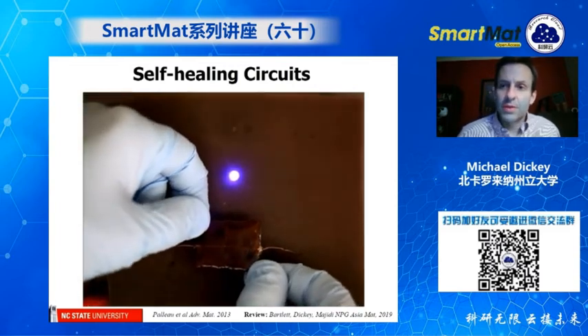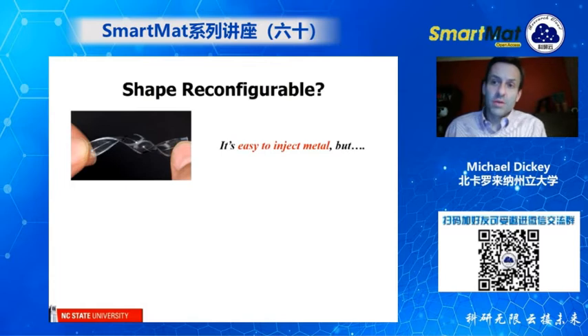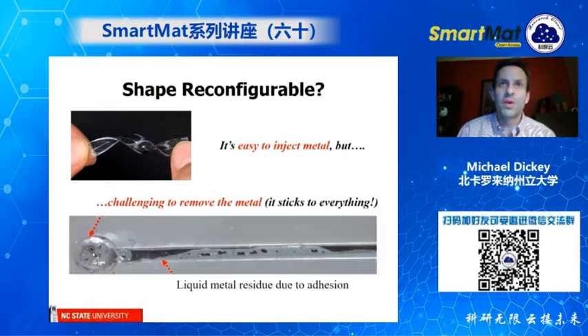Now, one of the interesting things about liquid metal is that you could potentially make circuits that change their shape. And so, as you know, it's very easy to inject liquid metal into these microfluidic channels, but it's not easy to pull it out. So if you try to suck the liquid metal out of one of these channels, you'll see that there's liquid metal residue. It sticks to the walls of these channels. In fact, liquid metal sticks to almost everything, which is very surprising because these liquids have very high surface tension. They should not stick to things, and it's only because of this oxide layer that they do.